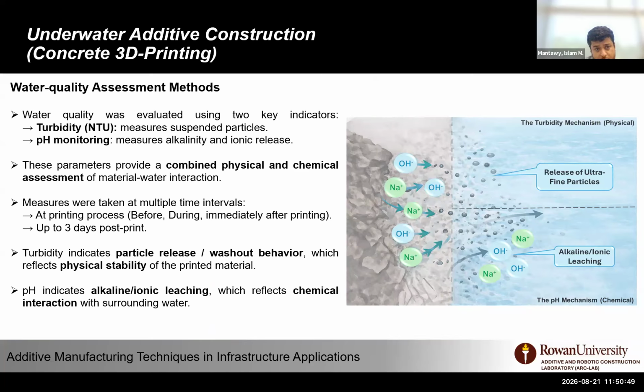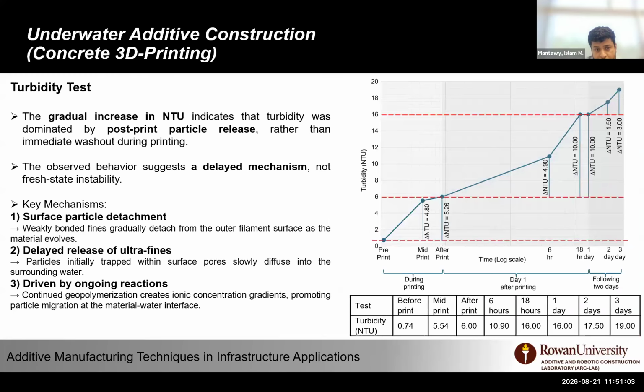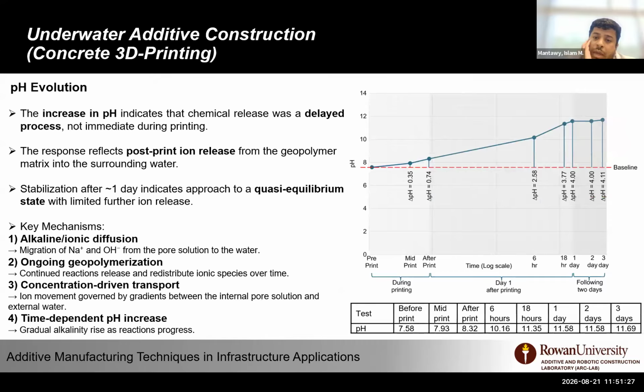One thing I mentioned is the low noticeable washout. We also worked on water quality assessment using pH monitoring and turbidity testing to test both chemical and physical washouts, especially since we are using chemical activators. So basically, we take water samples from the tank as we print: before printing, mid-print, after print, and every 6 hours, 18 hours every day for 3 days, and we do the turbidity test on it to see the physical leaching of the particles. We also did pH testing, which started at 7.58 for the tap water and increased to 11.7 because of the alkalinity in the mix.